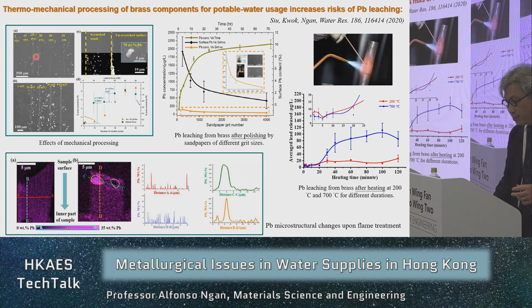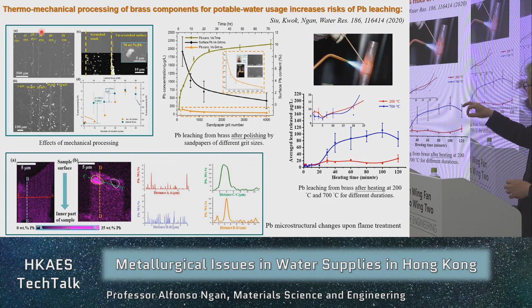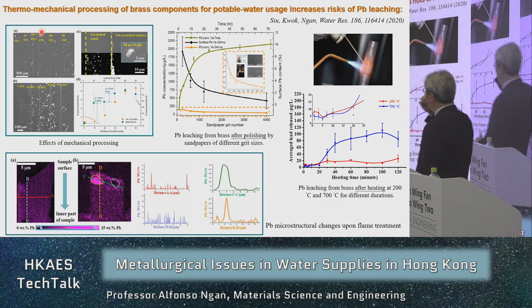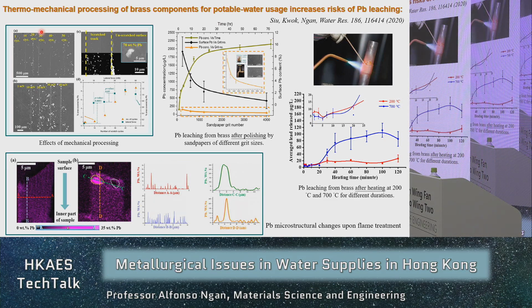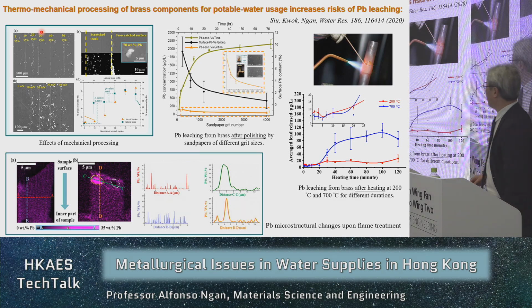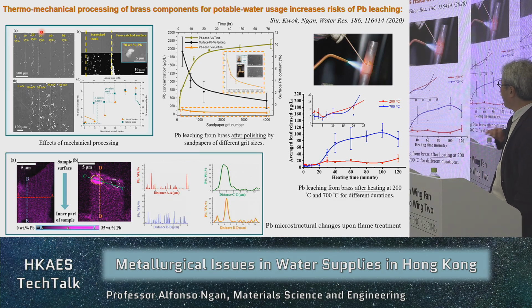In the laboratory, we did some scratch tests. We use a scratching machine. Those are the scratch tracks, okay? And then we use different scratching forces, and different numbers of cycles. The white bits were identified to be lead particles, okay? As you scratch a copper surface or brass surface, basically the lead will come out, all right? So that shows the result. For example, this green curve shows that the lead coming out would increase with time, okay?